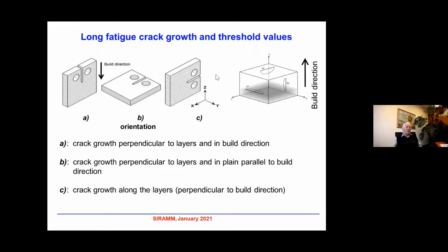We have prepared 3 types of CT specimens. There are specimens where the crack is initiated by cyclic loads from this notch, and then the crack is propagating in this direction, and we measure the fatigue crack growth curve. We have prepared 3 types of specimen again. Type 1 or type A is when the crack growth is perpendicular to layers. It is this one. Then case B is crack growth perpendicular to layers and in a plane parallel to build direction. And in case C, the crack growth is along the layers in this way, perpendicular to build direction.